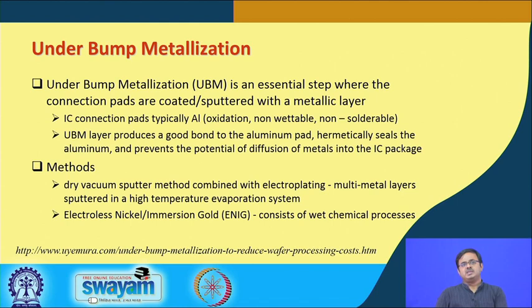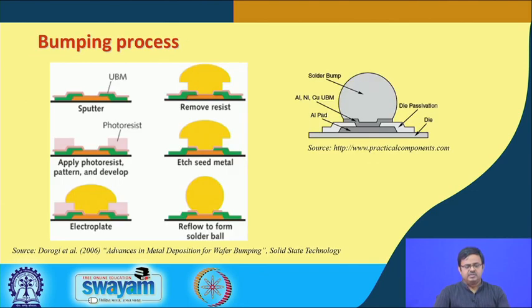The dry sputter method is still the most commonly and widely used, but the ENIG method, electroless nickel immersion gold, is also becoming popular. It consists of a wet chemical process, it is not a dry process. So, you have to do it in a wet lab, but it is said that the throughput of the process is higher compared to the dry vacuum sputter method in the evaporation chamber. Okay. So, that is UBM and that is the first step towards bumping of the die. All right. Next, we will look at the bumping process. So, bumping process involves what? It is the formation of the solder ball on the connection which now has the under bump metallized layer.